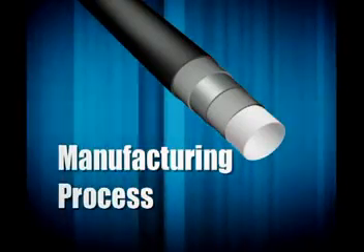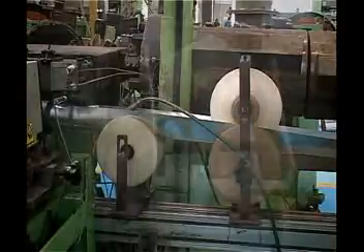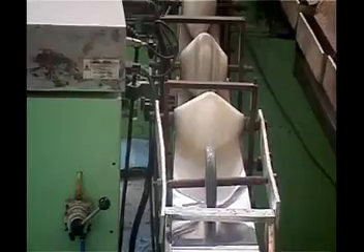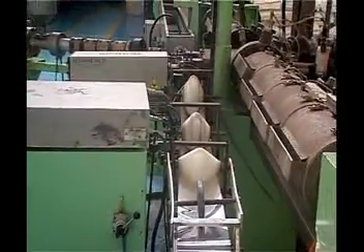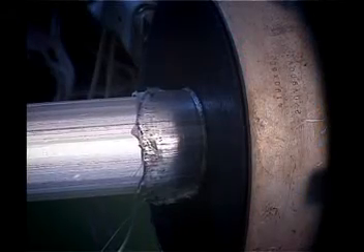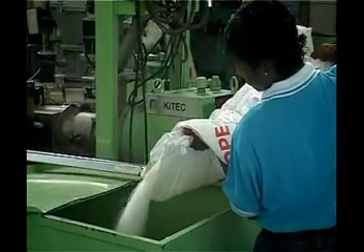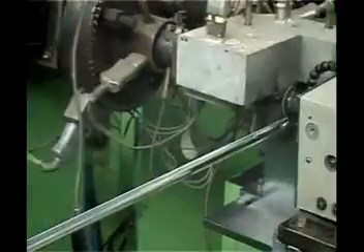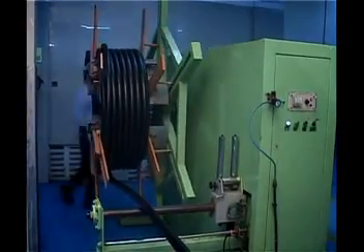KiTEC Composite Pipe Manufacturing Process. The manufacturing process is based on the forming and welding of an aluminum strip into a pipe, while concurrently extruding, via a sophisticated die head arrangement, layers of hot melt adhesives and polyethylene resins. In a short space, raw materials are fed into the system and finished pipe emerges, requiring only to be cooled down, coiled and cut to length.